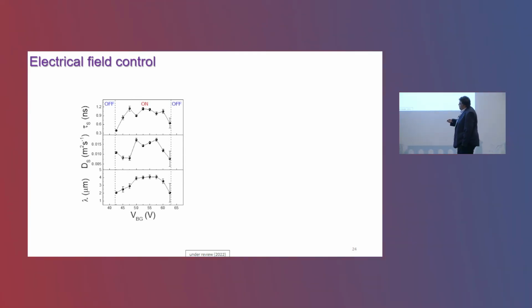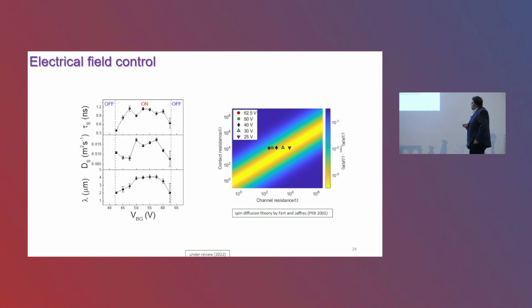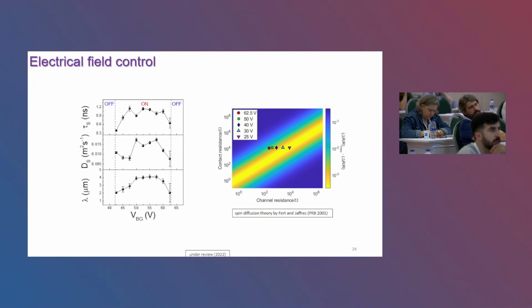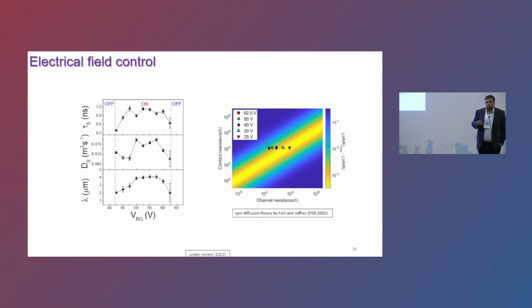Indeed, it already becomes conducting much before, but because of this conductivity mismatch issue, you still cannot effectively inject. Then there is a region where you can transport the spin current very successfully. And later on, even though the device is conducting very well, you again cannot propagate any spin current inside. It's just because you cannot effectively inject the spin current. We have done some very simple simulations following the Fert and Jaffrès spin diffusion theory. And what we see is that it's just coming from the conductivity mismatch issue kicking in because of the competition between the contact resistance and the resistance of the channel material.